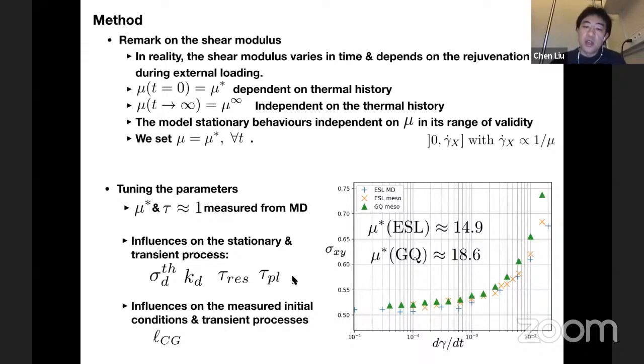So with these guidelines, we have the first results of fitting the flow curves. As you can see, for two samples that have two different thermal histories, their initial values of shear stress are quite different. This one has a larger value than the one that has a faster quench rate.